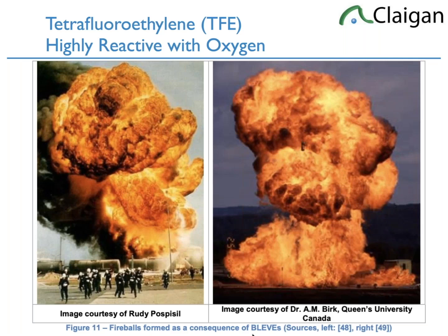And when it gets piped in, it gets put into water, and the water contains ammonium persulfate, and that triggers the TFE reaction. In this emulsion polymerization, TFE is a non-polar substance. Water is polar. It needs a surfactant like PFOA. It precipitates out into solid PTFE. The question is how much TFE is left over. Any PFOA in there is just surfactant that got caught up in polymerization. PFOA is the easiest way to control the particle size and grain structure by modifying it.